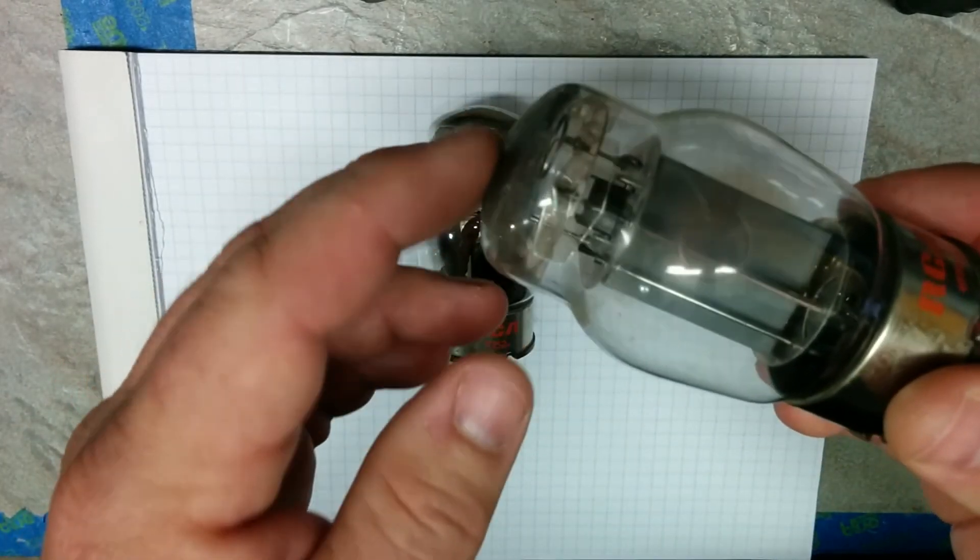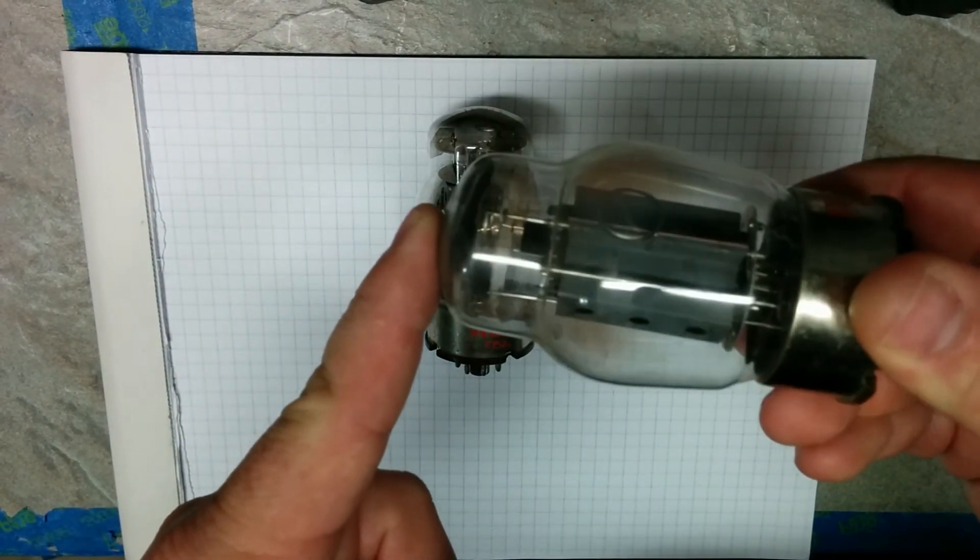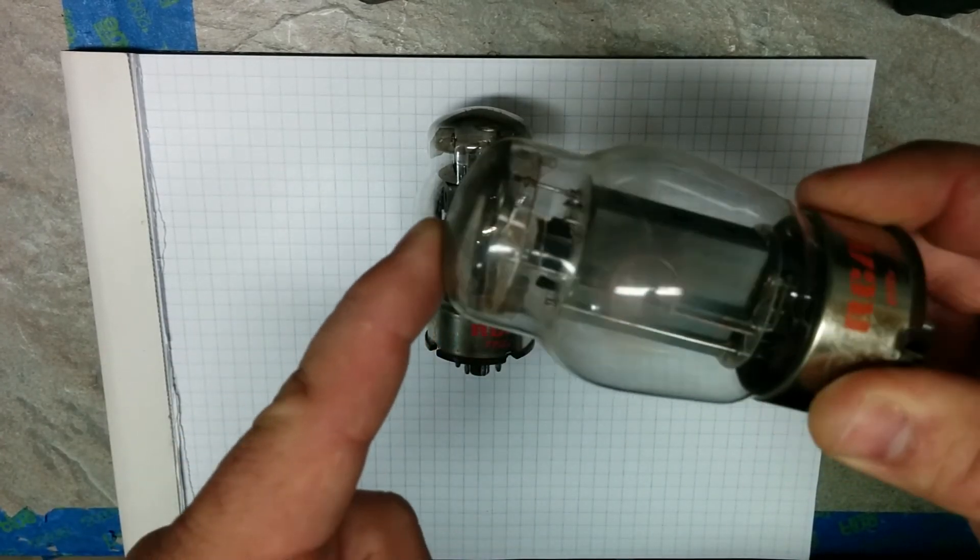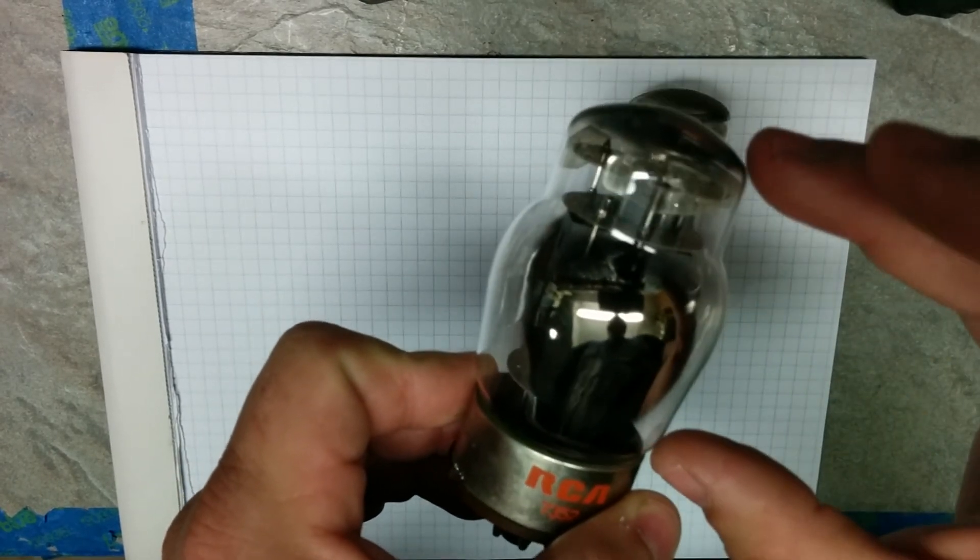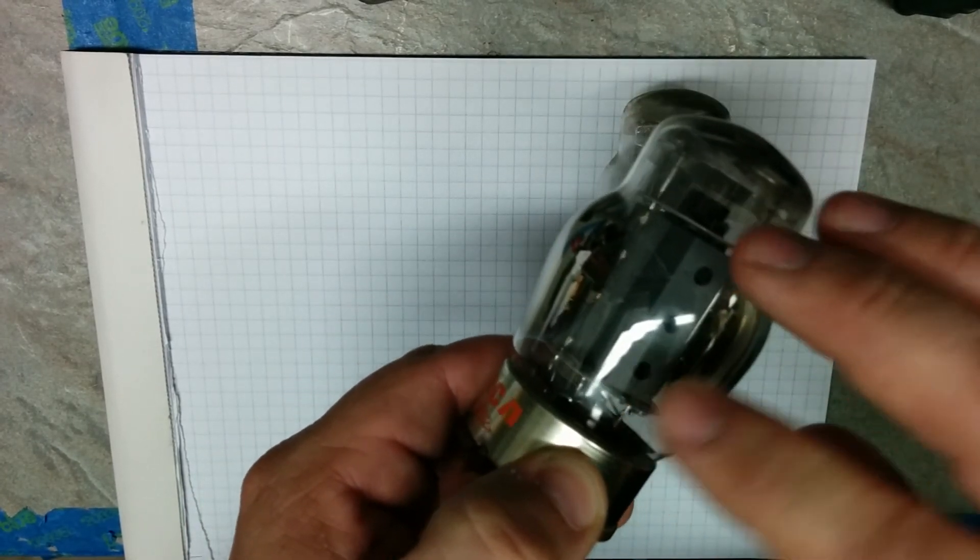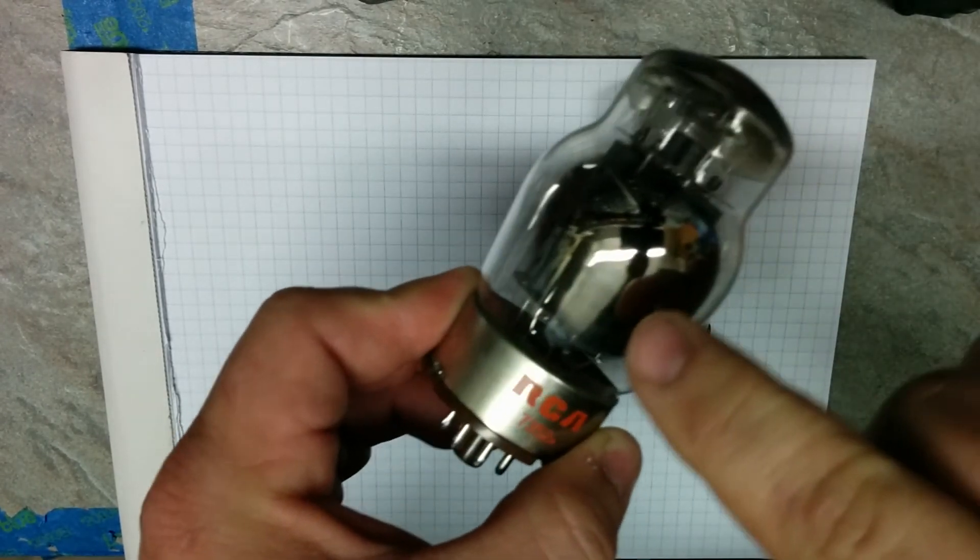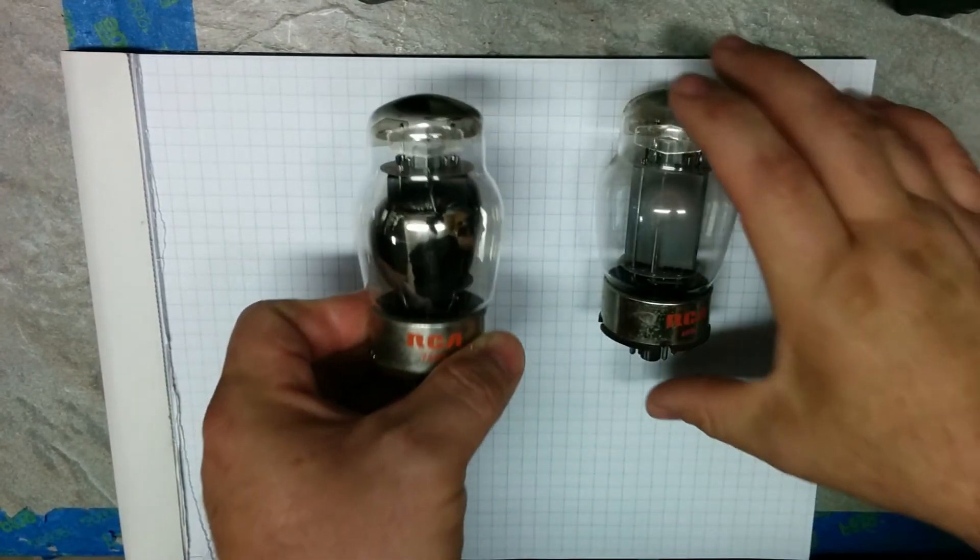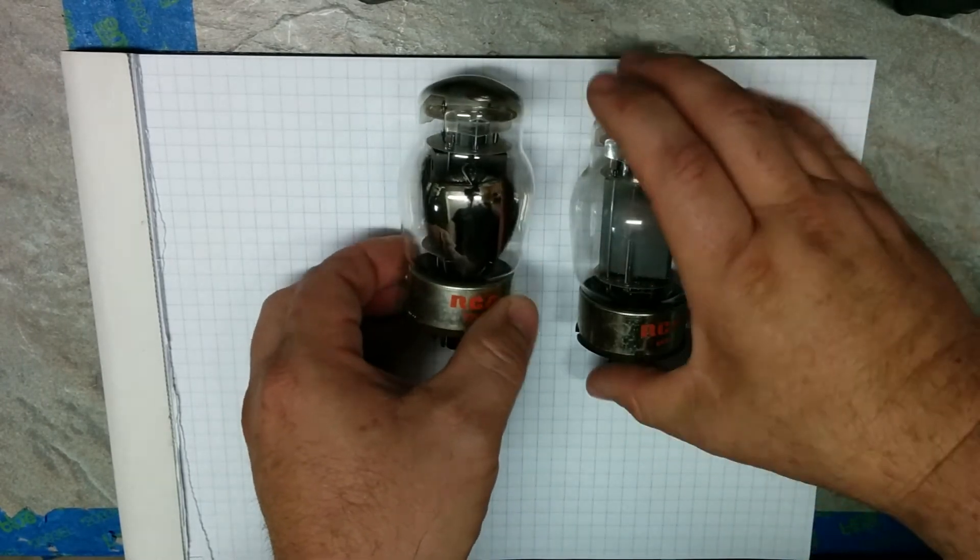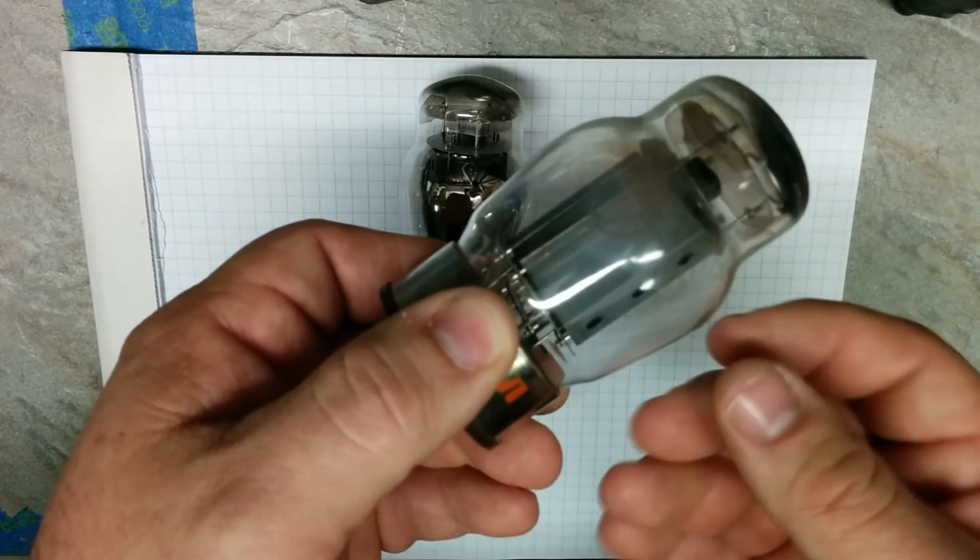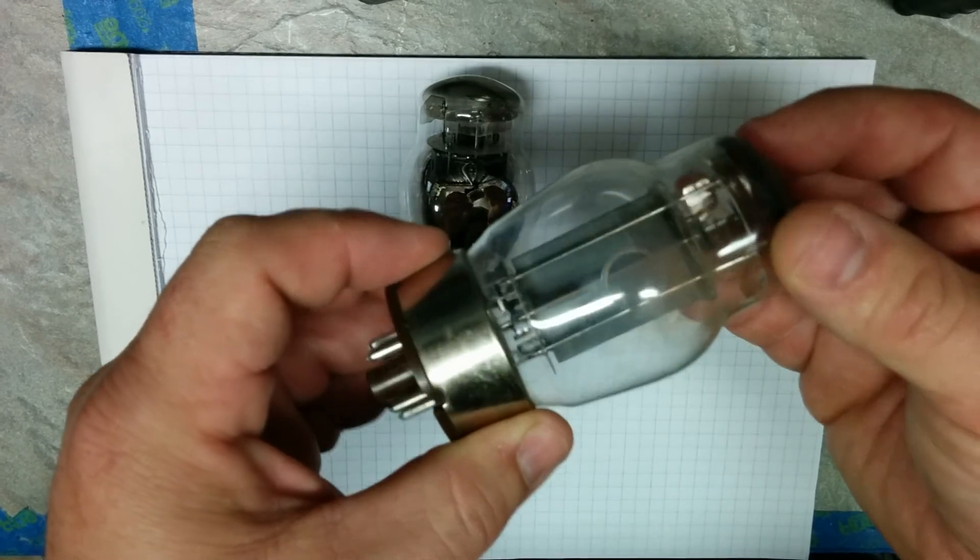This is the same kind of tube, but as you can see, you can see right through that getter flashing. It's basically not even there. It's just a little bluish, brownish haze that's left in there. What the getter flashing does is, as the tube ages, and no vacuum is totally perfect, some air or some gases that are either left in there from the factory or get in over the years are absorbed by the getter flashing. The more gases it absorbs, the weaker it gets. It gets discolored. And also from the heat and stuff in the tube. When there is almost no flashing left, all the absorbed gases have been kind of let back into the tube. And the tube is what's known as gassy. And that's bad.